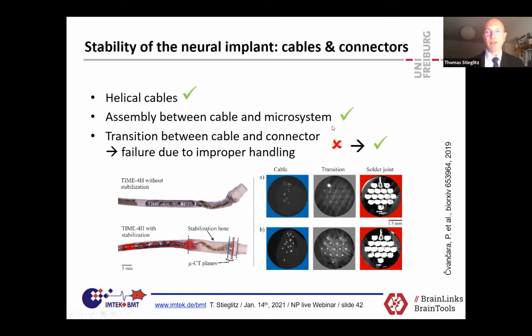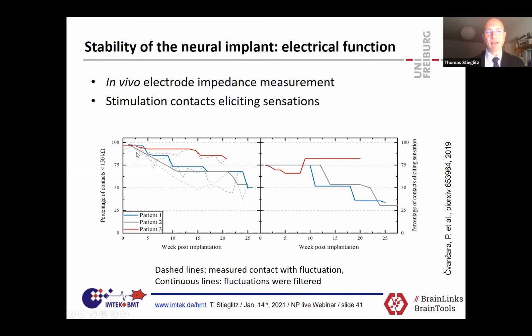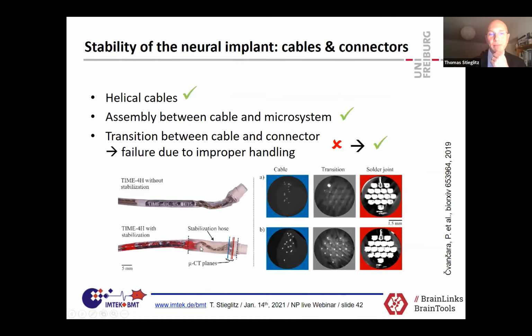And by that, as you see here in the upper row, all those wires broke, or a lot of wires broke here immediately in that transition and were no longer connected. And that is the reason, going back, why we had those dropouts here. Unfortunately, patient 1 and 2 were implanted shortly after each other. That means when we got the message, it was already too late to change the second implant. But we changed the implant for the third patient with a very simple thing, just adding more silicone rubber here so that you cannot really destroy that part. And the outcome was much better.